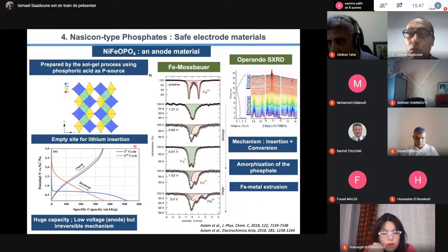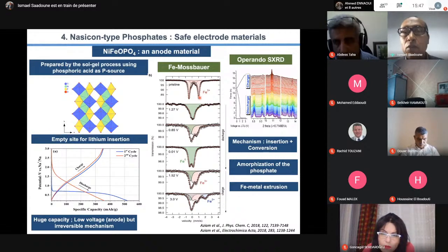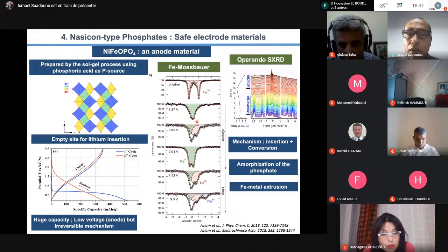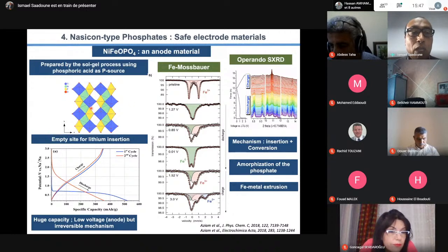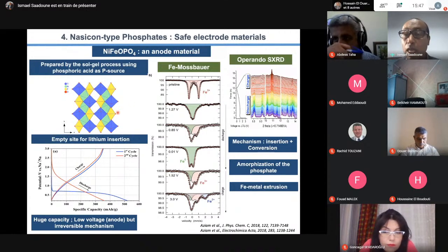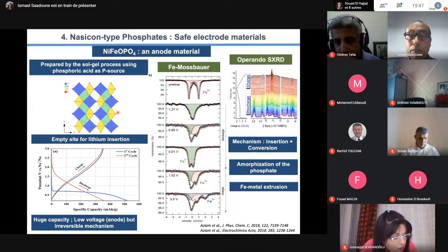To be sure, because we have iron here, we used iron Mossbauer spectroscopy on the starting material. We have the doublet of iron, but during discharge you see the appearance of iron triplets and the appearance of metallic iron. So the iron goes from the structure to metallic iron - this is extrusion, metallic extrusion of our phosphate. It was surprising, but it was possible to observe through this experiment.